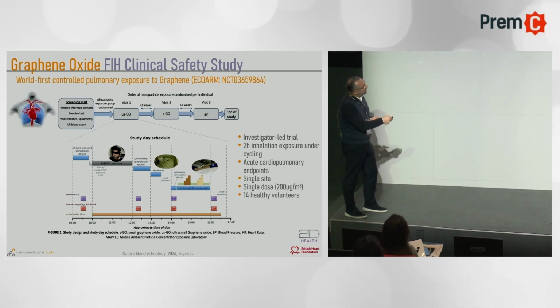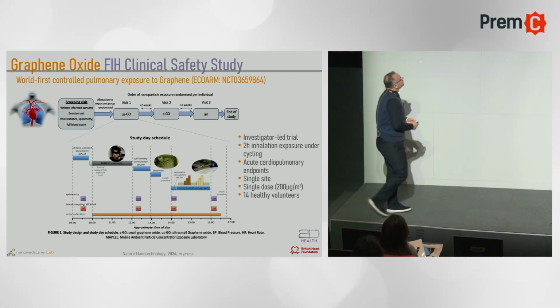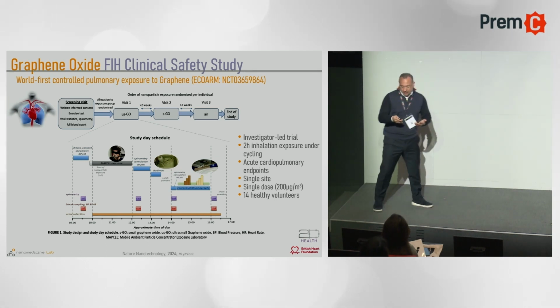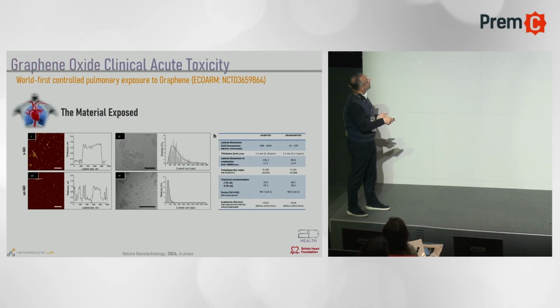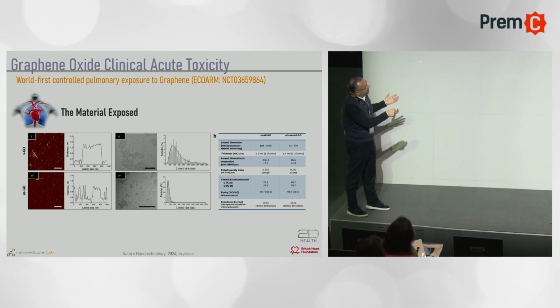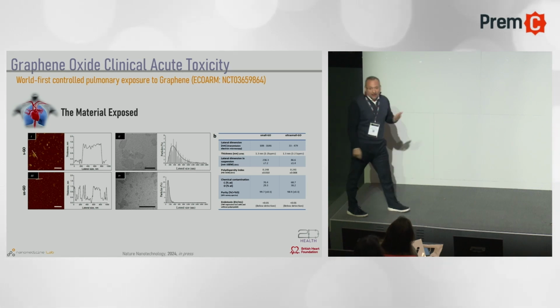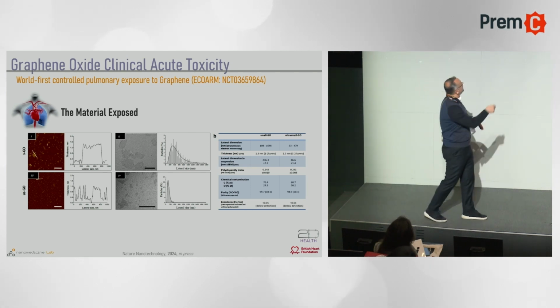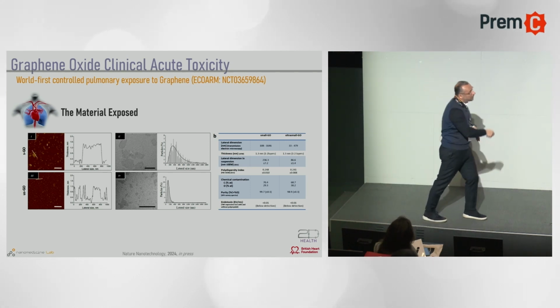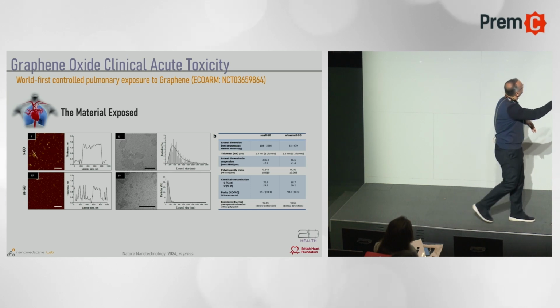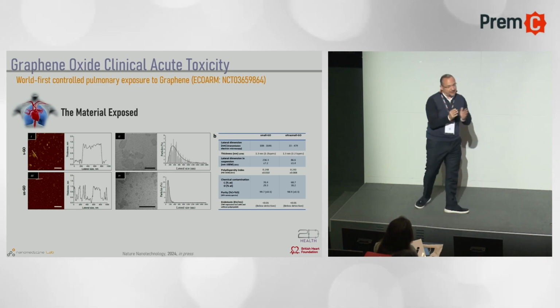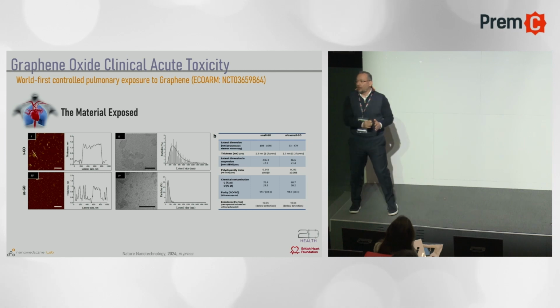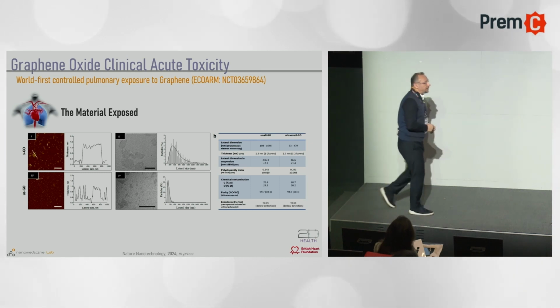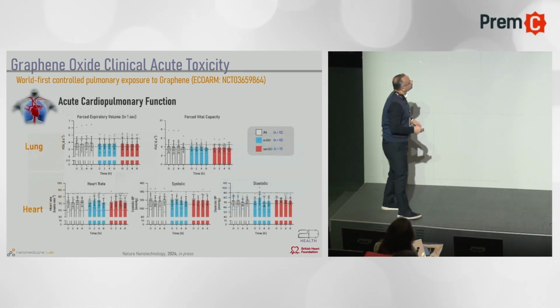And we had 14 healthy volunteers enrolled. I'm going to run through the data relatively fast in the interest of time. I just want to highlight again that the volunteers were exposed to either small graphene oxides, which are in the low hundreds of nanometers in lateral dimension, you can see here the distribution, and the ultra-small graphene oxides, which you see are much tighter in distribution. They are in the very low dozens of nanometers of lateral dimension.